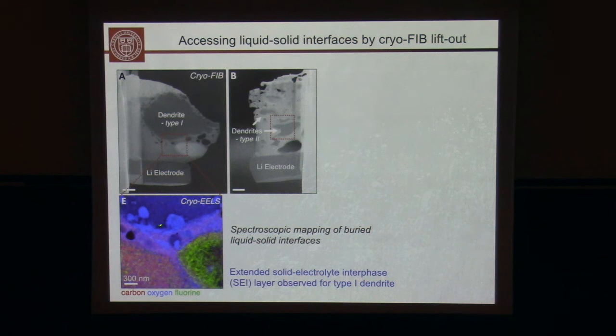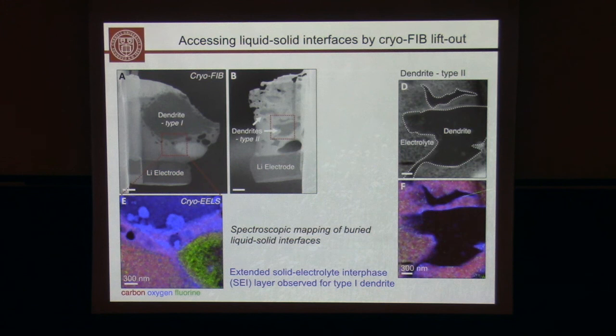And so what we observe, actually for the first time, is a very, very extended SEI layer. And the reason why, we believe, it hasn't been previously observed is that usual techniques to study them involve washing of the battery. And that means any soft materials that are around your electrolyte will be washed away, you lose them. And so here we can look at the elemental distribution, but not only at the elemental distribution, but also how the bonding varies as you go across this SEI layer. So dendrite 2 looks dramatically different. You see that it has only a very, very thin oxygen-rich SEI layer at the surface, much more what you would usually expect the size of an SEI layer should be.